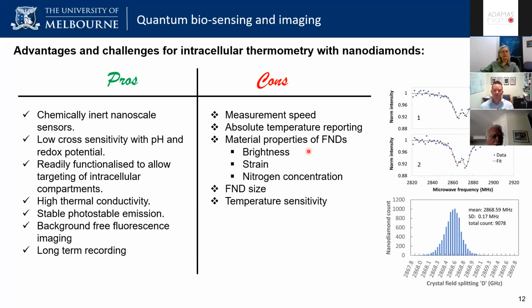And then I think there are a whole bunch of material properties that can be improved in terms of the brightness of the particles, the strain. So the strain has a significant impact, and the nitrogen concentration has a significant impact in terms of the ODMR spectrum itself. So here is an example of the ODMR spectrum from some of these nanodiamonds. And you can see that there's what we think is Stark splitting from the fact that the nitrogen concentration in these materials is really high. And so you end up seeing this Stark splitting, which broadens this peak significantly. So that impacts the temperature sensitivity, for example.